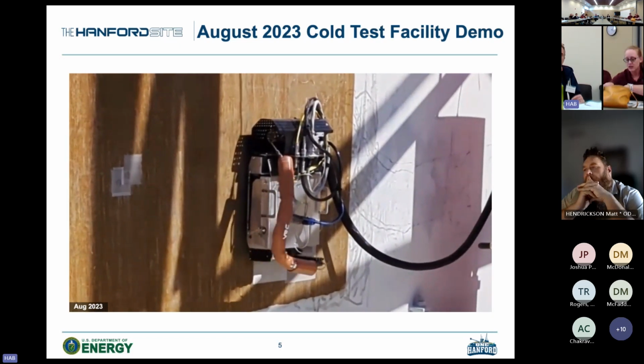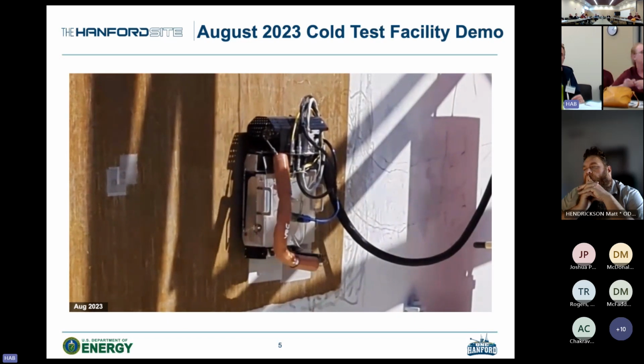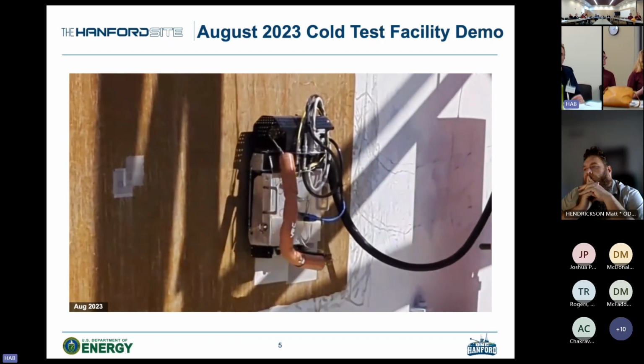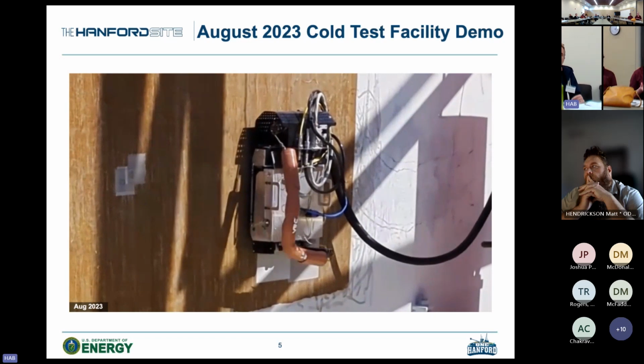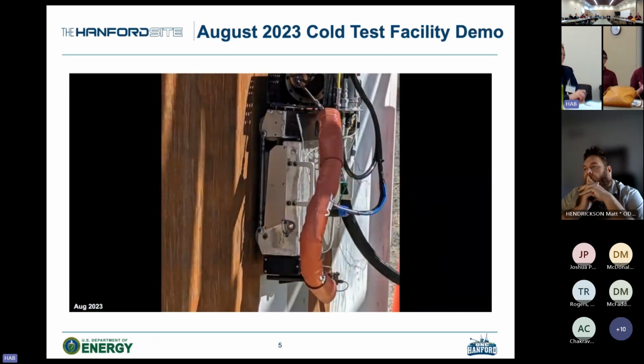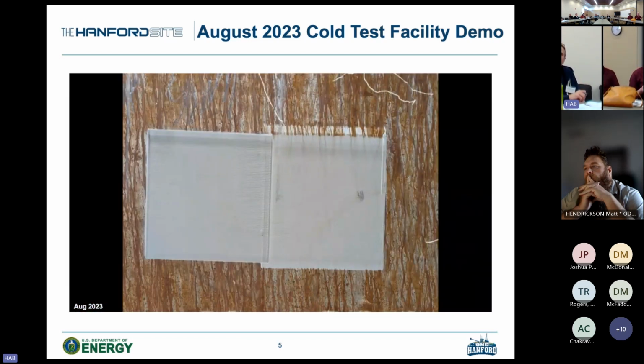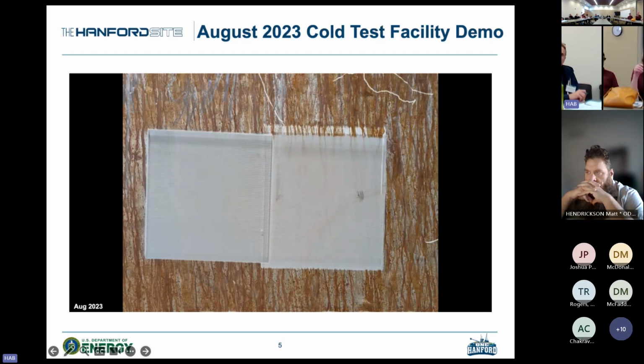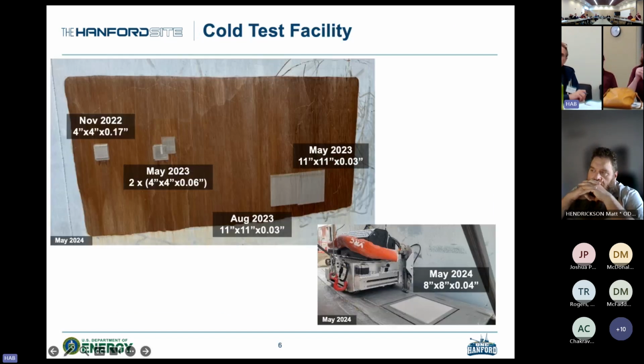And what I want to talk to, which is not shown, is that we perform coupons. We spray coupons in the field before and after we actually spray the true patch. That way we can analyze if the system is performing as anticipated and desired. So this is one such coupon that you would generate out in the field. This is a mild steel with 410L stainless steel on top. So you can pass that around and see that coupon material. So again, that's the stainless steel on top of a carbon steel.